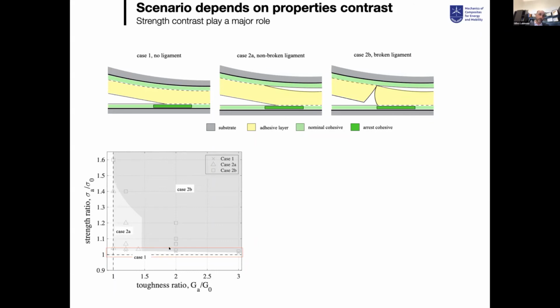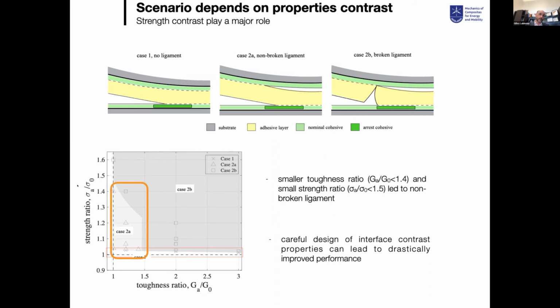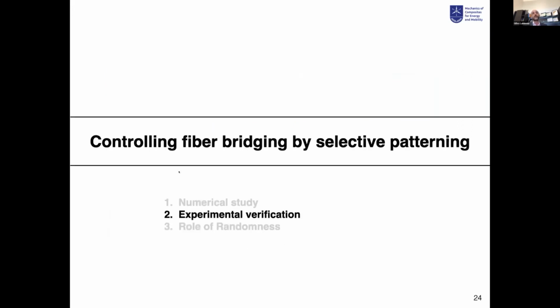And what you realize when you make simulation on this is that in fact you can completely predict this by numerical simulation. You have a design space that tells you that if I have a certain ratio in strength and a certain ratio in toughness between these two domains, I have a certain window here for design where I can control for sure that I'm going to create ligaments that are going to introduce this toughening effect. So this is something that you can verify experimentally.